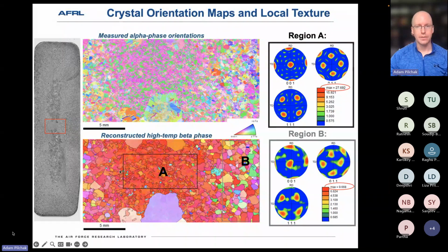And the first thing that jumps out is this region A, what was all of these greens and purple colors here. It reconstructs back to essentially a single orientation that's comprised of a whole bunch of low misorientation subgrains. And so this is the corresponding pole figure for that. You essentially see a cube-like texture there, but again, there is some distribution about that average nominal cube orientation. When we get out to region B, we do see some remnants of that cube orientation still. Texture intensity has fallen quite a bit, and the size of the spots on the pole figures, so the distribution of orientations, is also a little bit larger.